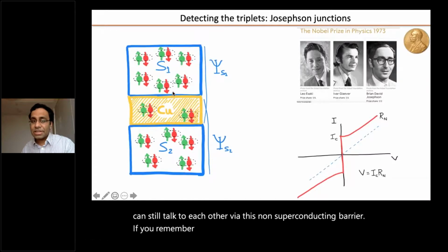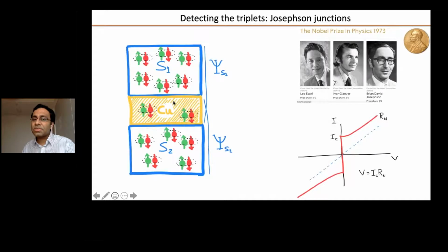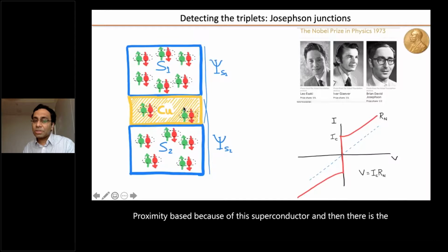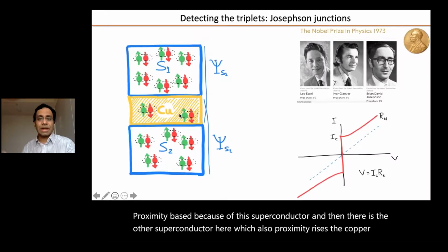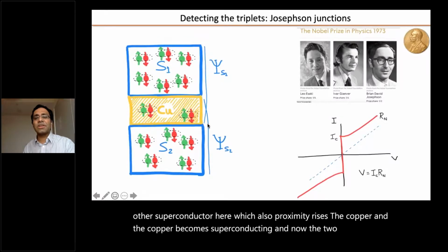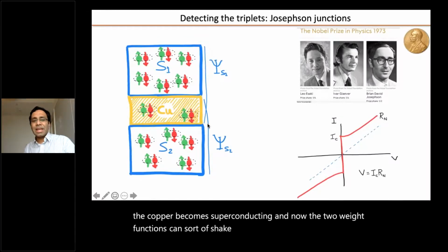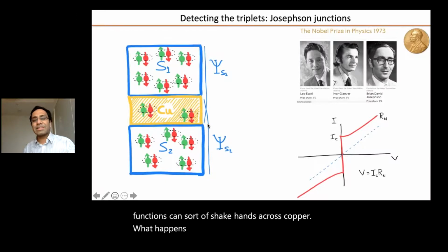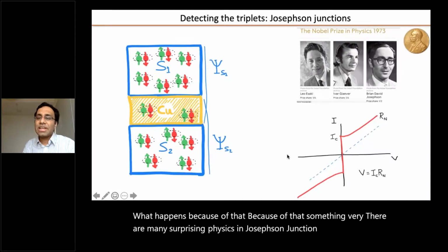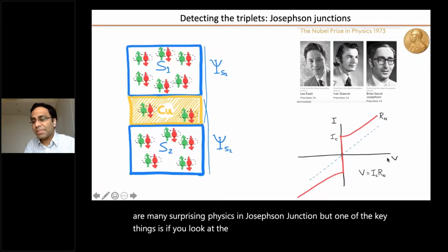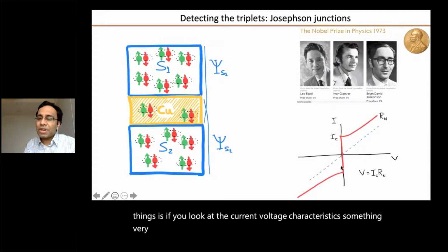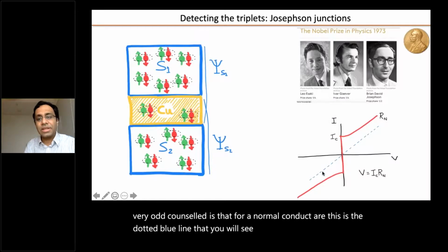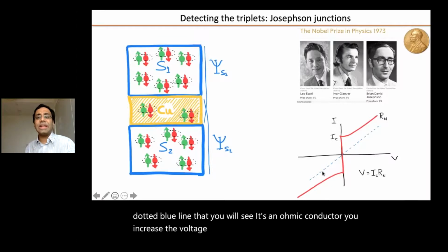If you remember this proximity effect that we discussed, the copper becomes a bit proximatized because of this superconductor. And then there is the other superconductor here, which also proximatizes the copper, and the copper becomes superconducting. And now the two wave functions can sort of shake hands across copper. What happens because of that? There are many surprising physics in Josephson junctions, but one of the key things is, if you look at the current voltage characteristics, something very odd comes out. For a normal conductor, this is the dotted blue line that you will see, it's an ohmic conductor. You increase the voltage, you increase the current, and there is a linear relationship.